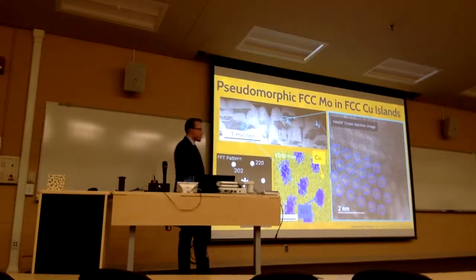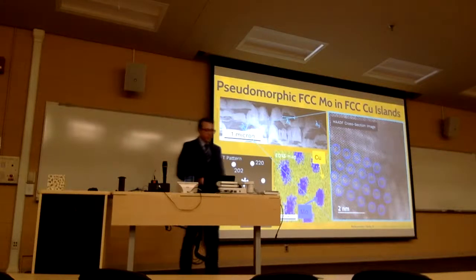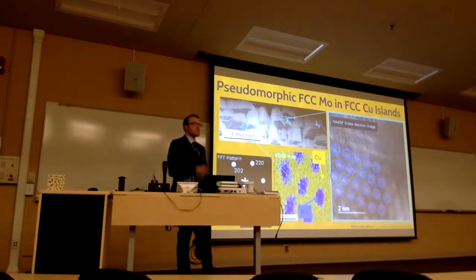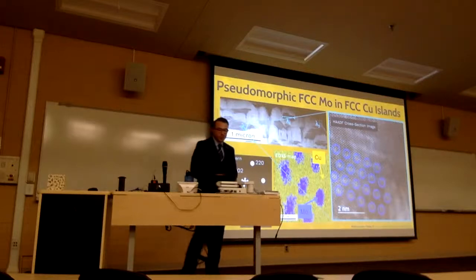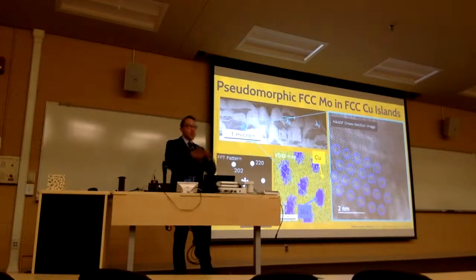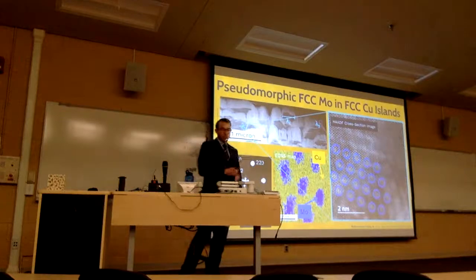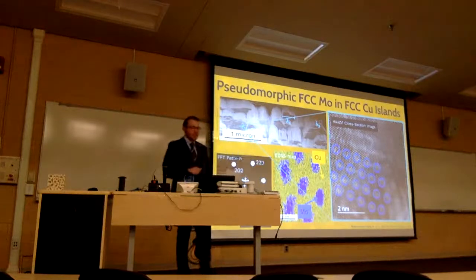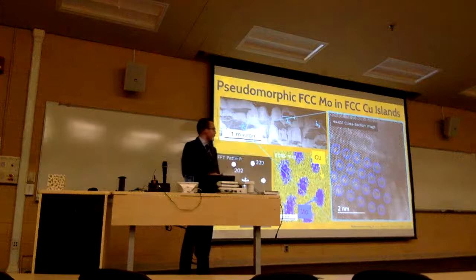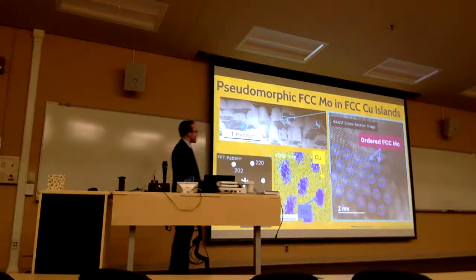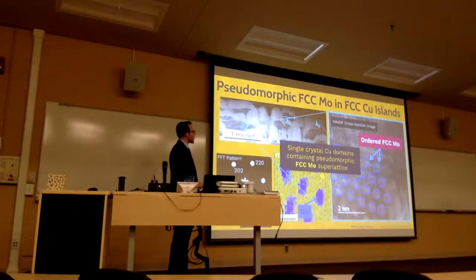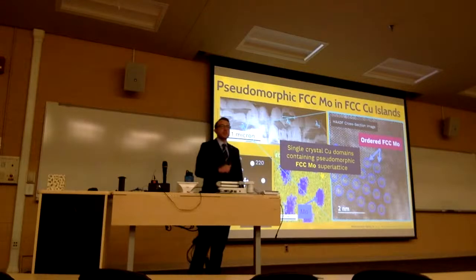We actually measure the crystallography of the high resolution image of the sample in fast Fourier transform. We can only pick up frequencies from the face-centered cubic crystal structure, which suggests to us that this whole matrix is actually FCC crystal structure, which actually, if you consider moly, is metastable. Moly would prefer to be in the BCC crystal structure. So what we have here is ordered FCC moly particles inside that copper domain. So what we have is single crystal copper domains containing that metastable or pseudomorphic FCC moly superlattice.